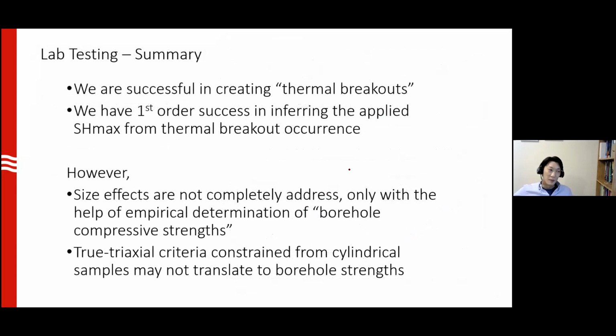So the summary from this lab testing is that phenomenologically, we are successful in creating this thermal breakout, and we have first order success in inferring what the far field SHmax magnitude is. But there's certainly effects that we are not totally comfortable with yet. One is the size effect, which we could only address empirically. And then also the fact that this true triaxial criterion that we constrain from cylindrical samples does not really apply to the borehole geometry.